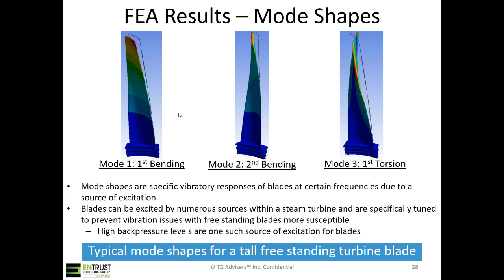Overall, these blades can be excited by numerous sources within a steam turbine. And then these larger later stage blades, especially freestanding blades like this one, must be specifically tuned to prevent any vibration issues. Freestanding blades are going to be the most susceptible to vibration problems, so that's why a lot of those design features that we discussed earlier are usually implemented, whether it's some sort of tip shroud arrangement or just something to tie the blade tips together, and potentially something to tie the mid spans of the blades together as well. In steam turbines in particular, high back pressure levels are one such source of potential excitation for L-0 blades, your last stage blades.